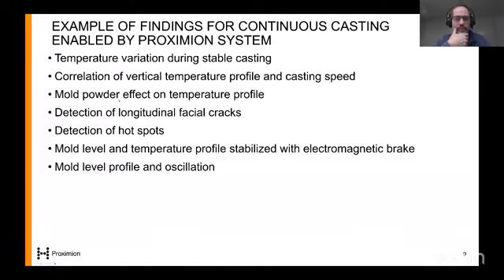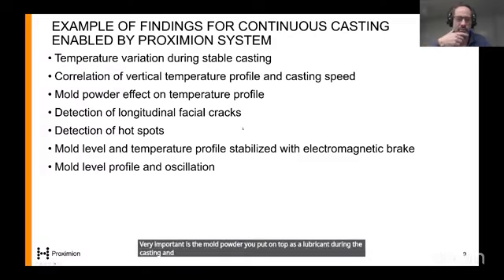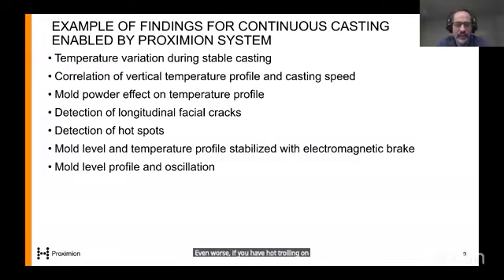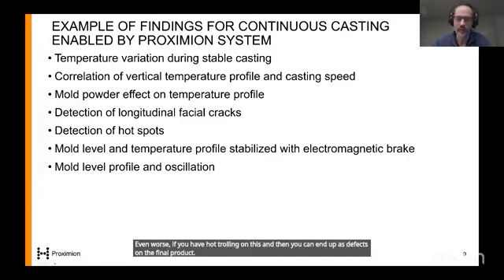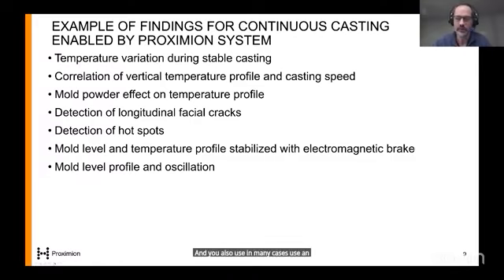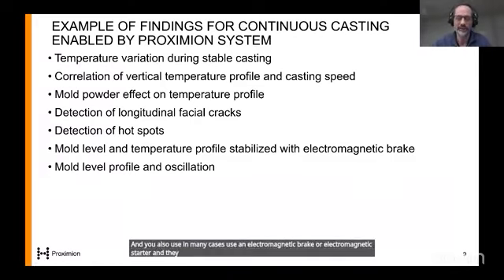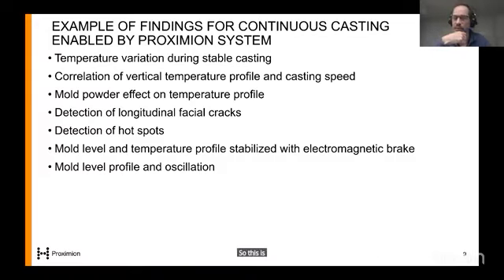Very important is the mold powder you put in on top as a lubricant during the casting, and its effect on the temperature. A common problem is cracks on the surface, which are quite expensive to remove. Even worse, if you have hot rolling afterwards, you can end up with defects on the final product. In many cases you also use an electromagnetic brake or electromagnetic stirrer, which will affect any electric sensor. So it's good that you can monitor the system while the brake and stirrer are on. That was not possible with a thermocouple.